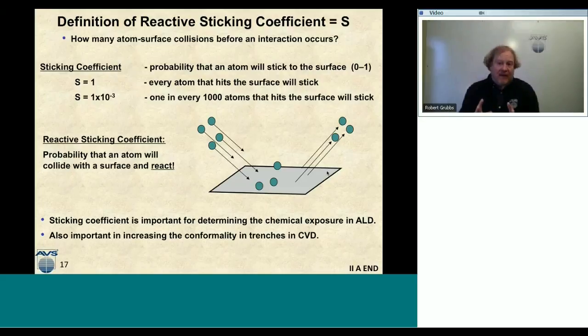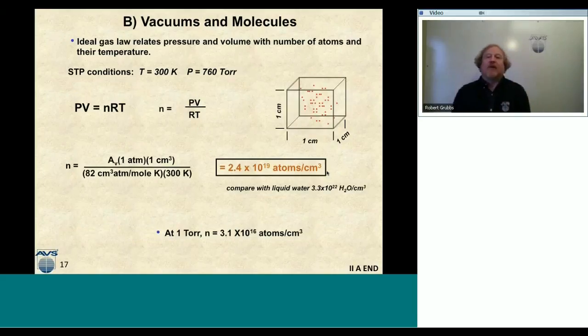But in chemical vapor deposition, if my reactive sticking coefficient is low, that molecule in the trench won't necessarily all collect at the top of the trench. It'll kind of ping pong down to the bottom, and then I can get a better, more conformal coating of a trench structure in CVD if I pay close attention to the sticking coefficient of my precursor molecules. So that's just as a side note, but reactive sticking coefficient is very important whether you're talking about ALD or also CVD. So that concludes the section on surfaces,